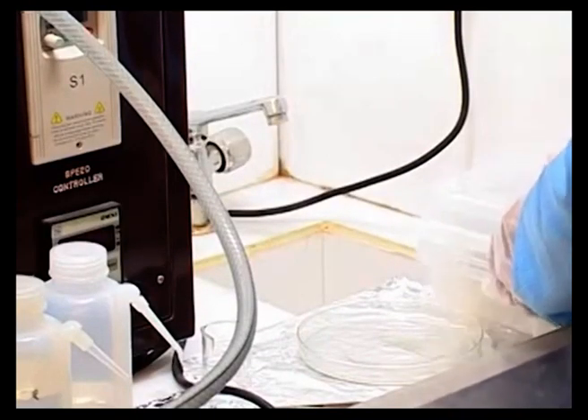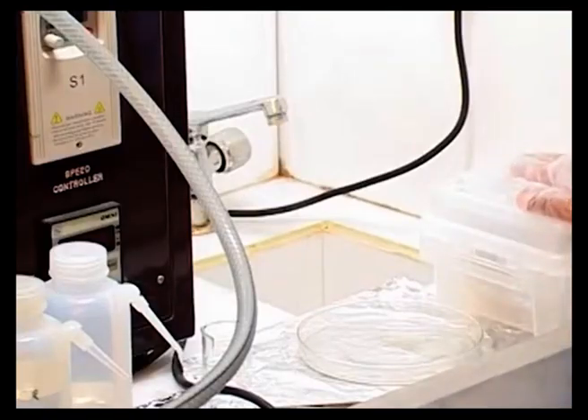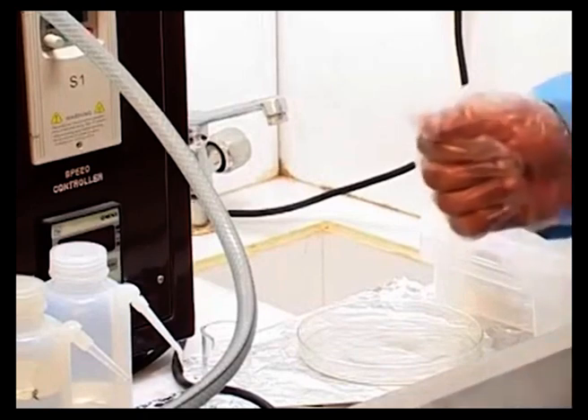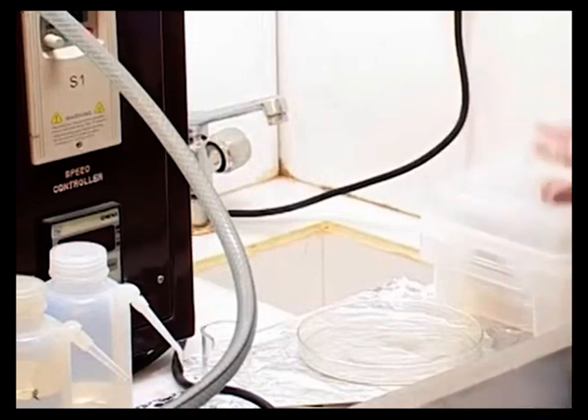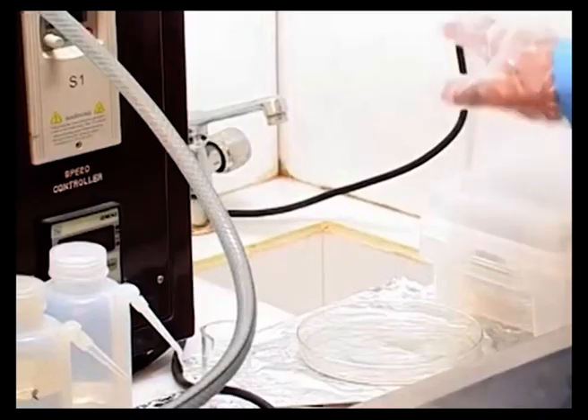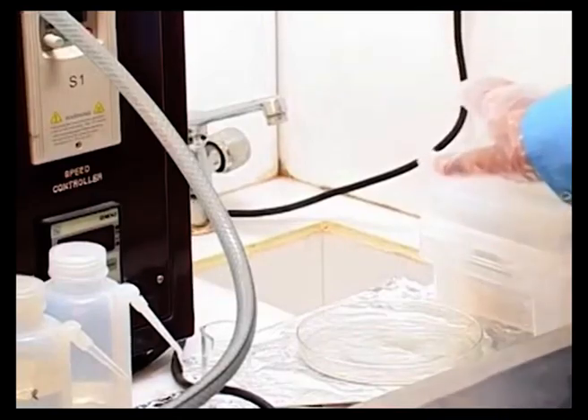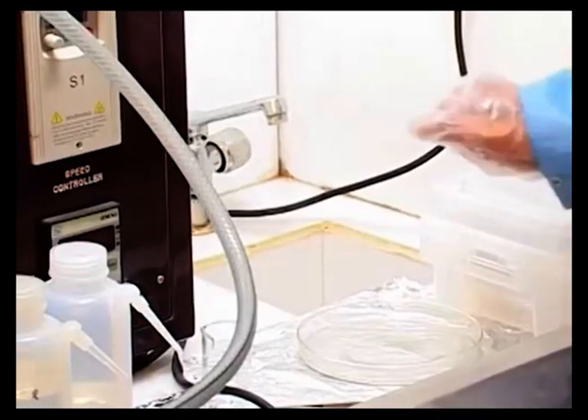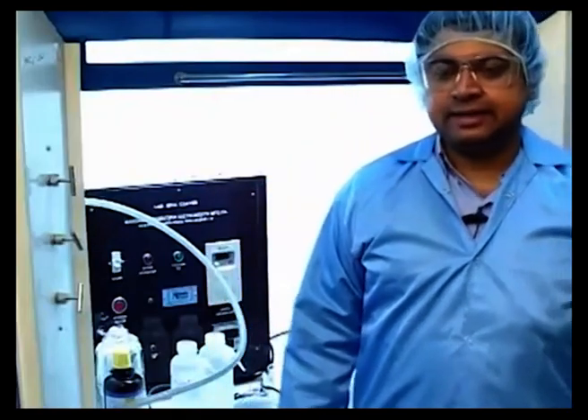One of the reasons is that we have to be extremely careful while handling silicon wafers, because they are very fragile and essentially can crack even on little impact or stress. So we have to make sure that this wafer box is far away from the experimental setup, at least the main box is far away from the experimental setup. So the next step basically is the clean wafer.